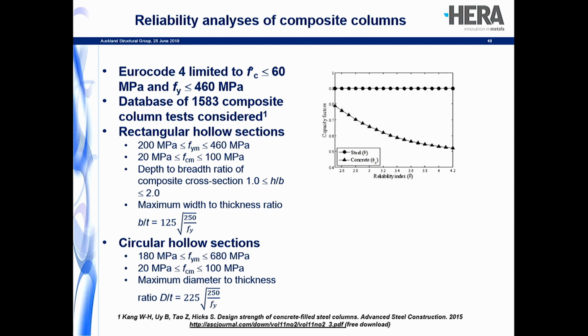And again, similar to what we did for beams and studs, we ended up doing some reliability work on this, going back to scratch. So Eurocode 4 only permits cylinder strengths up to 60 megapascals and yield strengths up to 460 megapascals. To enable us still to apply the rules to 100 and 680 megapascal concrete and steel respectively, we also did some reliability work.